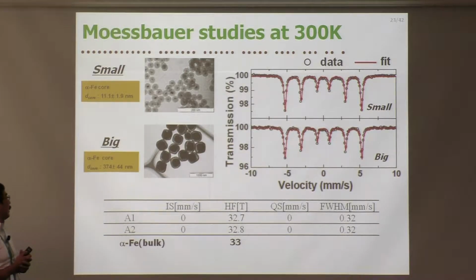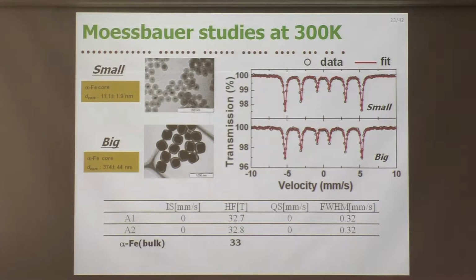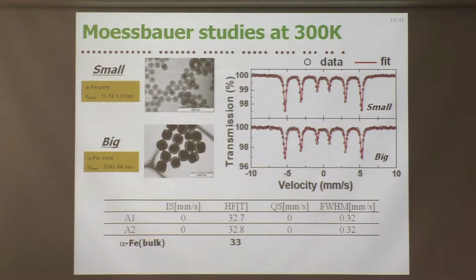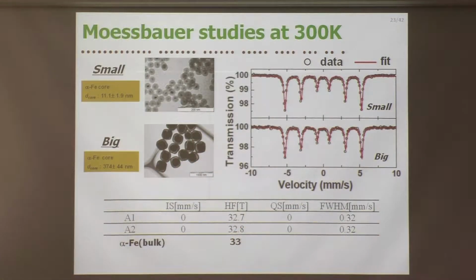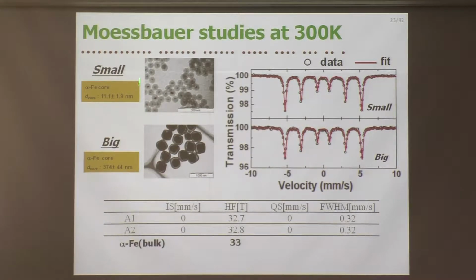Here I'd like to talk about the magnetic properties. At first, the microscopic magnetic properties. We carried out a Mossbauer spectroscopy measurement, which is a very sensitive tool about the microscopic environment of the iron atoms. Here we show two results, from two samples: one has a small iron core, the other has a big iron core.